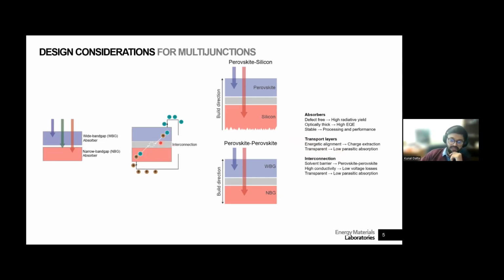The interconnection layer that I just mentioned, in the case of a perovskite tandem, also needs to act as a solvent barrier, because as you can imagine, if you're doing both the cells with solution processing, the solvents for the deposition of the second cell will affect the first cell. So this layer in between needs to be quite dense and therefore protect the underlying device.